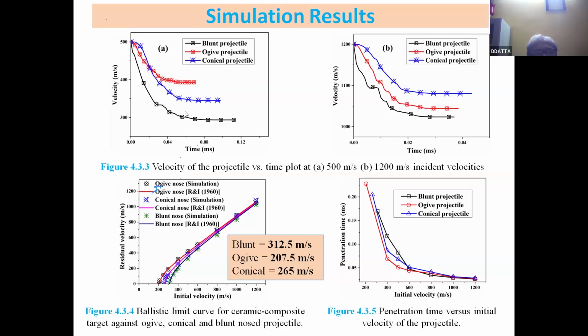So these are the plots for blunt nose, ogive nose, and here you can see the strike velocity and the time. This is velocity versus time of perforation, residual velocity. So blunt nose gives a ballistic limit velocity of 312.5 meter per second. Ogive nose 207.5. Conical is 265 meter per second.